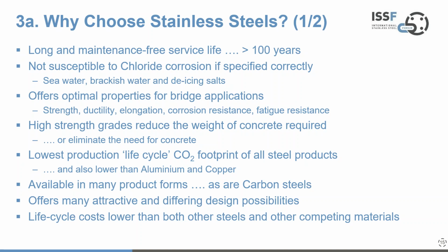Now, stainless steels, if specified correctly, are not susceptible to chloride corrosion, and that includes seawater, brackish water, and de-icing salts, as I've previously mentioned. In terms of properties for bridge applications, particularly duplex stainless steel, you've got this wonderful combination of strength, ductility, good elongation, good corrosion resistance, and good fatigue resistance. And again, it's all about choosing the right grade in the family for the right environment. The high strength grades reduce the weight of, say, concrete required, or even, and I'll show an example when we showcase a few, the need for concrete completely.